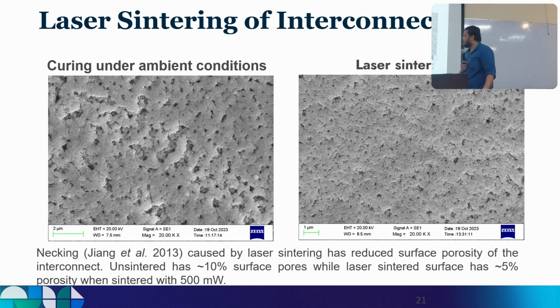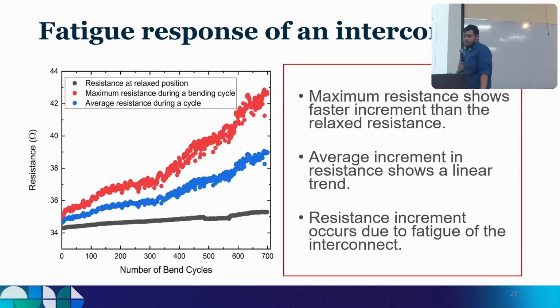This is a closer look at the image that I showed you before. This is under 20,000 magnification, and you can clearly see the larger pores in the electron microscope image of the cured interconnect compared to the laser sintered image. So we can determine that laser sintering is a good method of sintering.